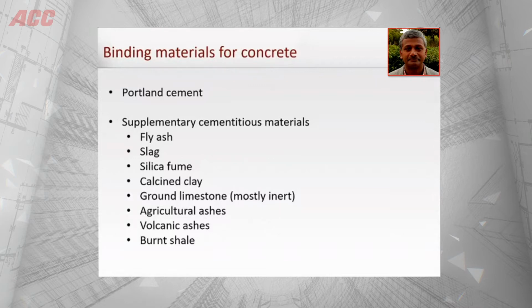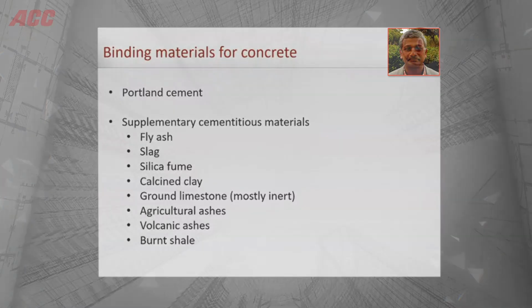The principal ones being fly ash, slag, silica fume, calcined clay, ground limestone, which is mostly inert, but it has some interesting chemical characteristics. We'll talk about that a little bit later. We also use, in some situations, agricultural ashes like rice husk ash or sugarcane bagasse ash. And in some cases, when it's available, volcanic ashes have also been used as cement replacement. Burnt shale, again, where it's available, could be a useful replacement for cement and function well as a supplementary cementing material.